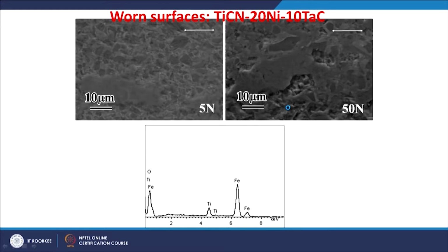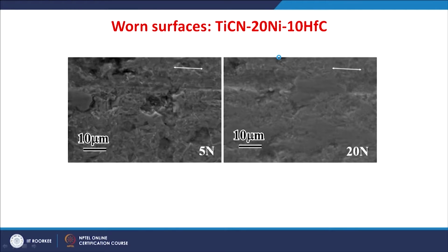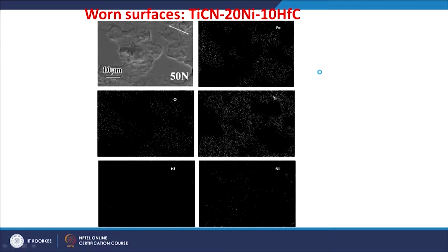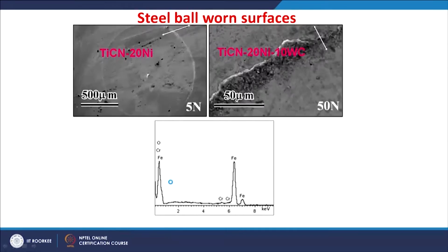The cermet was titanium carbonitride, nickel and tantalum carbide. Again it shows coverage by the tribolayer at higher loads. So, the hafnium carbide containing cermet shows very severe pullouts and cracked material, whereas again at higher loads there is a layer formation. The X-ray mapping of these cermet materials after sliding at higher load also indicates, see, this is the layer and this is rich with iron and oxygen, whereas these layered areas do not have any nickel or hafnium or titanium.